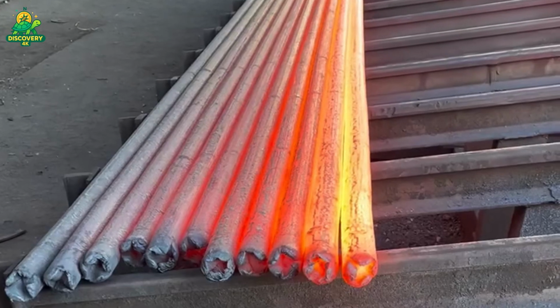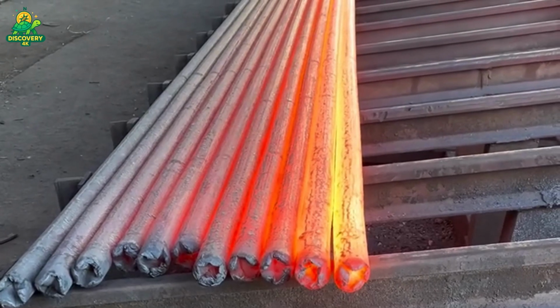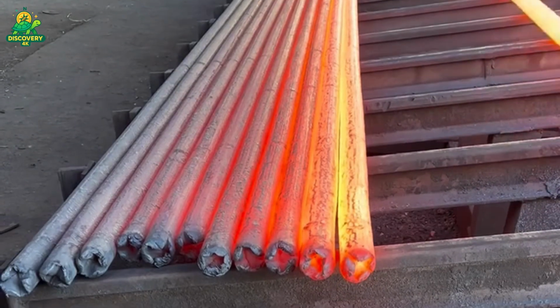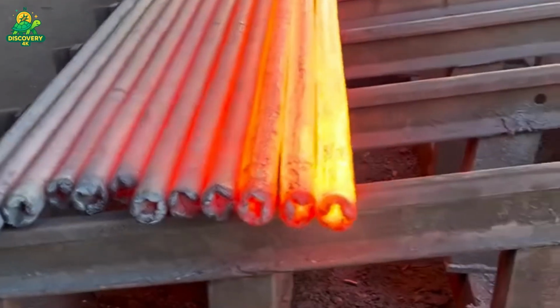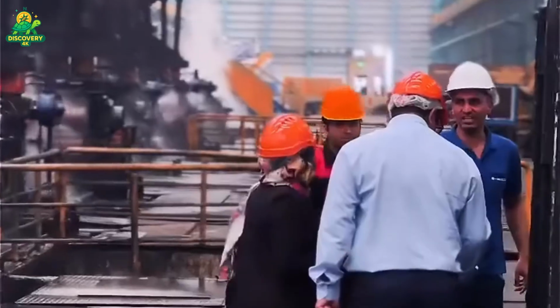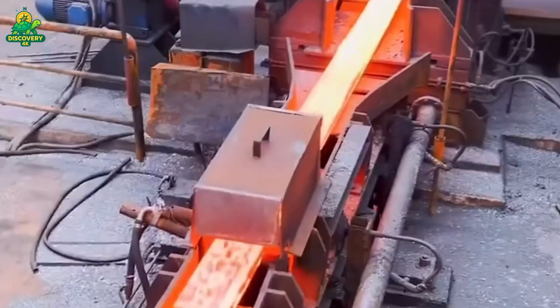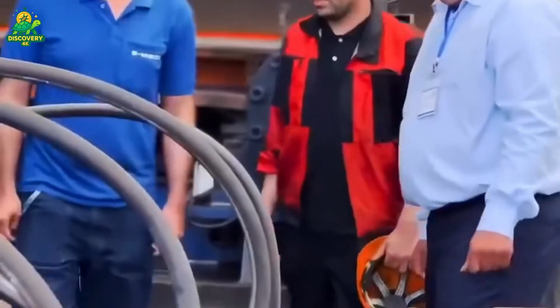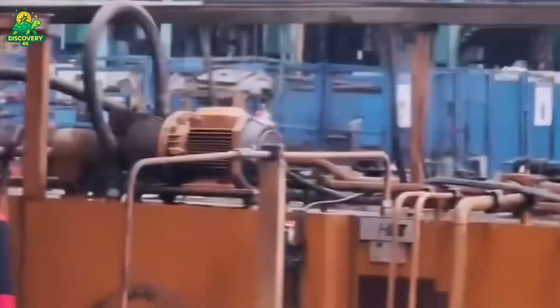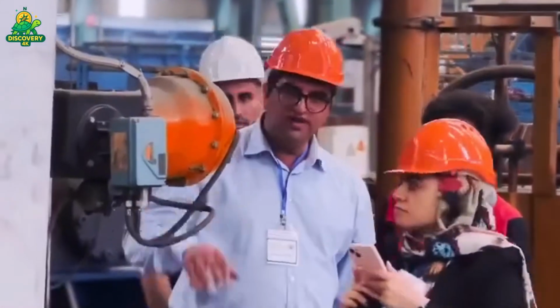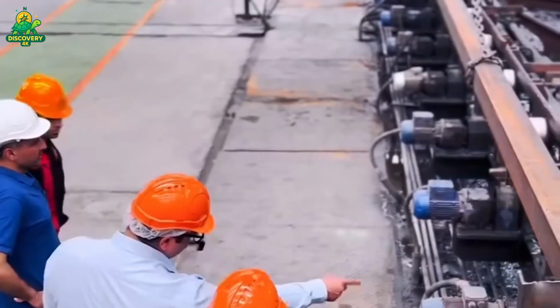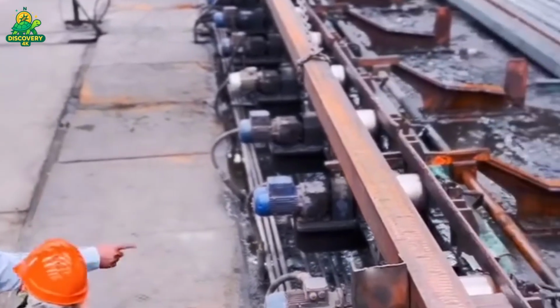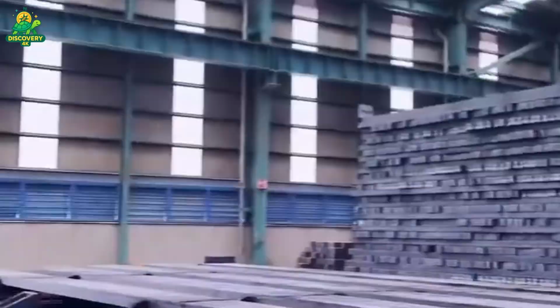Molten steel is poured into a mold that quickly cools it into a semi-solid shape, typically a square billet about 6 to 8 inches wide. The billet then travels through a series of rollers and water sprays to fully solidify while maintaining its shape. This continuous casting method is faster and more efficient than traditional ingot casting, with virtually no waste. The red-hot billets are then cut to length and sent to the reheat furnace for the final forming stage.